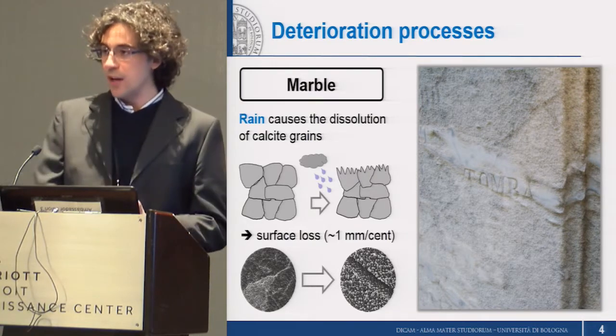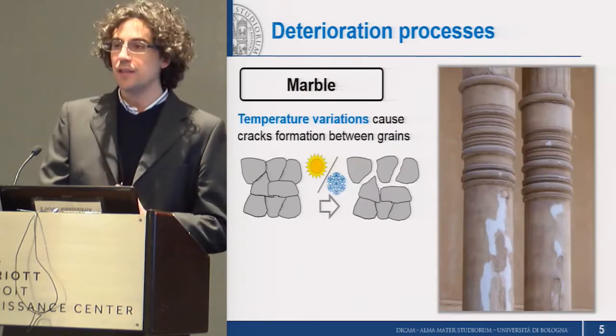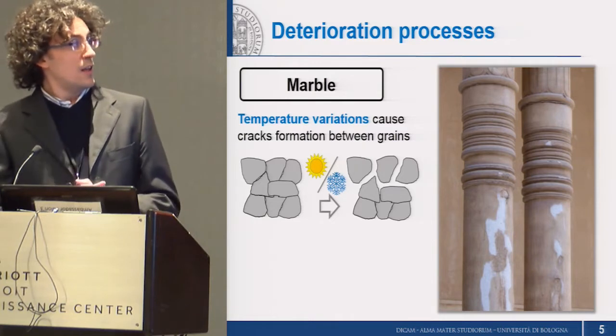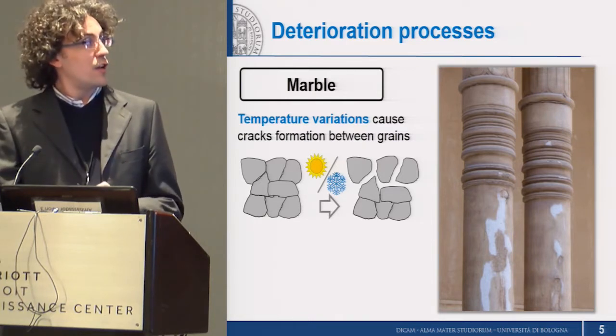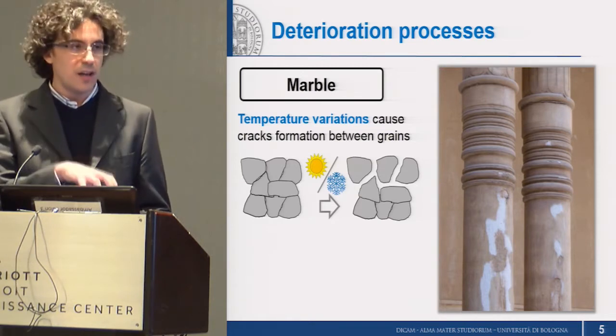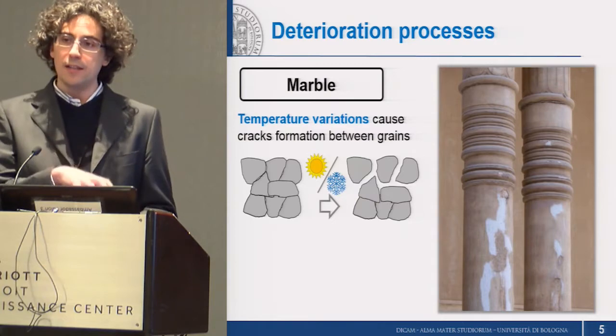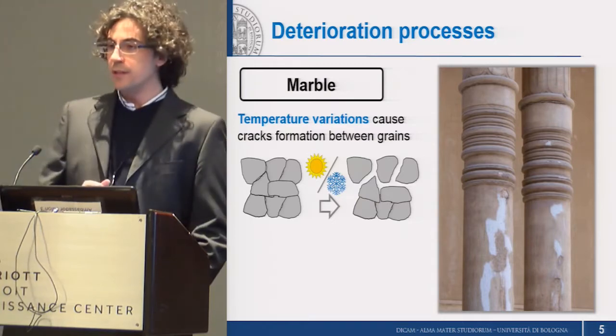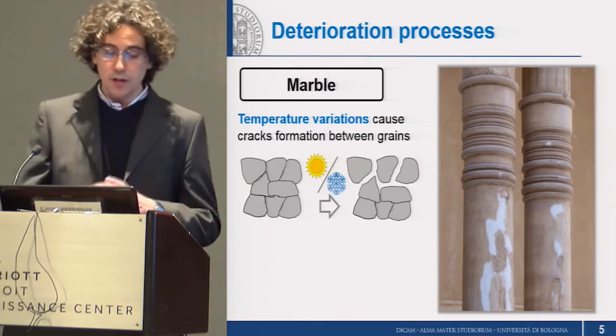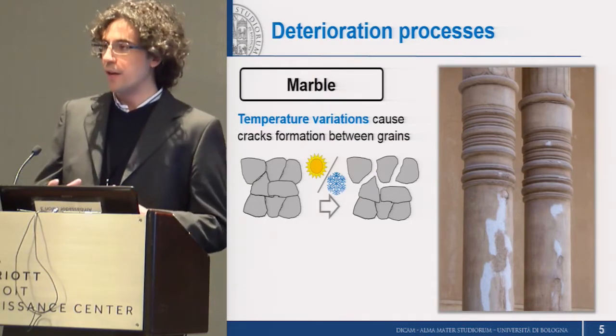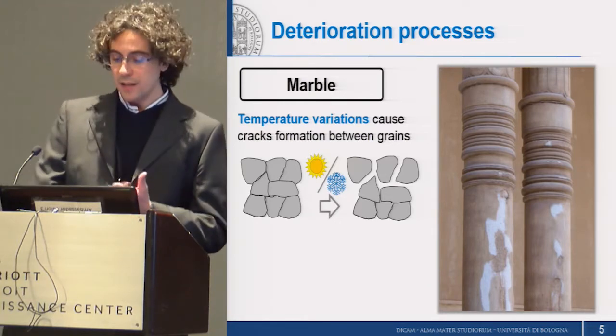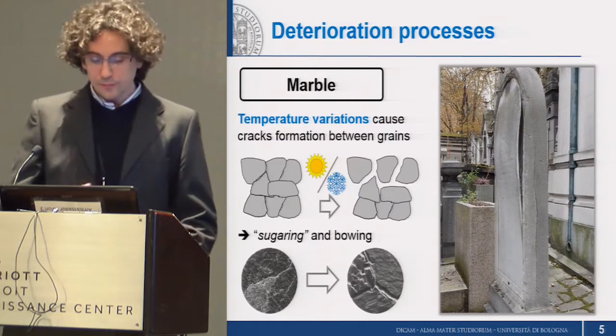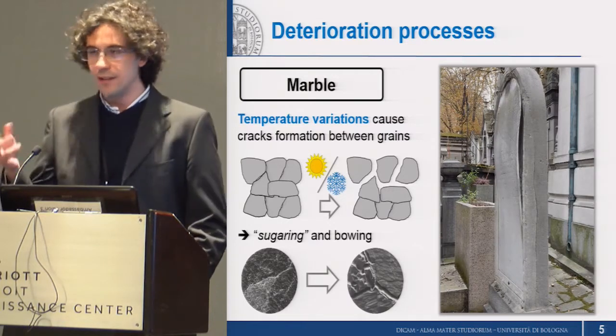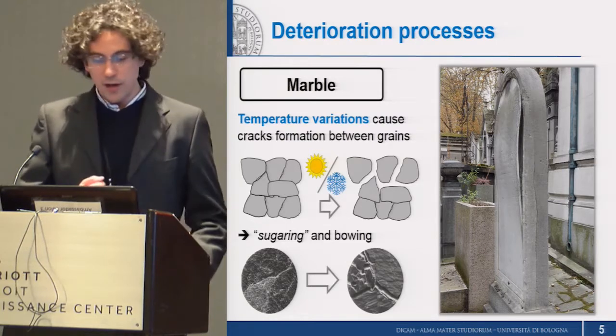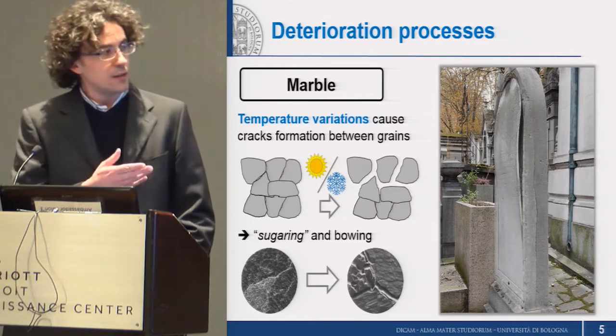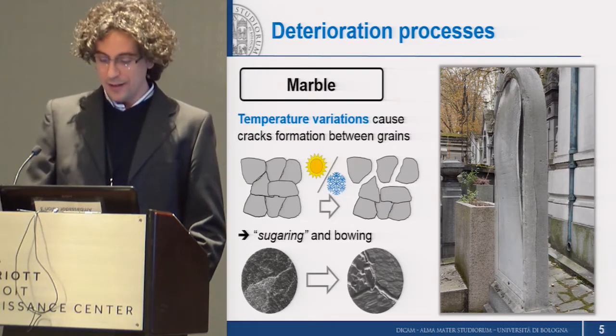At the same time, just because marble is non-porous, it is highly sensitive to another peculiar phenomenon, the so-called thermal deterioration, because calcite crystals behave anisotropically when they are subjected to temperature variation. So repeated heating-cooling cycles, meaning day-night temperature variations, can cause the opening of microcracks at the boundaries between grains, which give rise to the so-called sugaring, which means that calcite grains literally fall apart, and the spectacular bowing that affects both, in this case, a gravestone in a cemetery in Paris, but also slabs used for cladding new buildings.